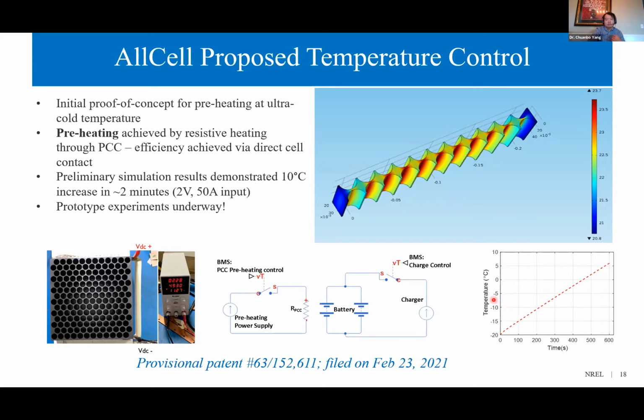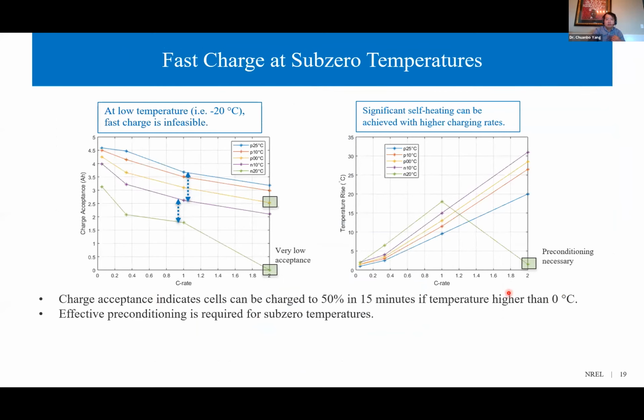Proof of concept for preheating was carried out with 3D finite element simulation. The result demonstrated a 10 degrees Celsius increase can be achieved in about 2 minutes. With the phase change composite heating, a prototype experiment is in progress so far. Based on the study,